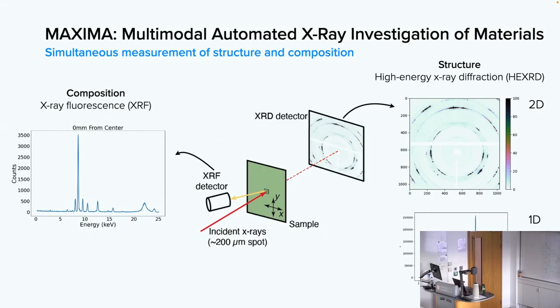So here's our sample. It could be several centimeters in extent. It's a foil, maybe a few hundred microns thick. Our X-rays now are focused to about a 200 micron spot. They're high enough energy that we can go through that sample and record an X-ray diffraction pattern in transmission. So here's an example here.